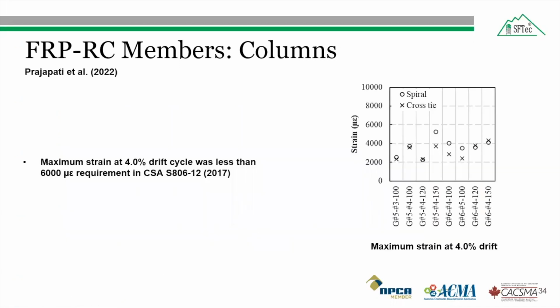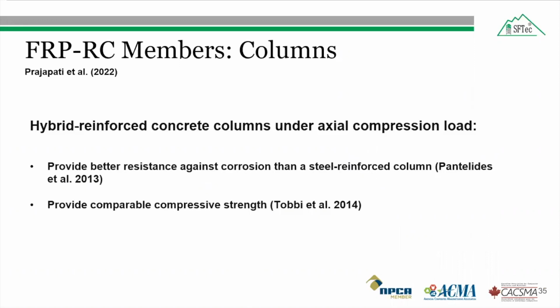The maximum strain attained by all the GFRP spirals and cross ties was lower than 6,000 microstrain, which was lower than the requirement in the CSA S806 design code. The GFRP spirals and cross ties don't show any failure for most of the tested columns, which shows their effectiveness in confining the concrete column core. Glass fiber reinforced polymer reinforced concrete columns could be suitable for medium rise structures in low to moderate seismic zones. The compressive behavior of GFRP bars in GFRP reinforced concrete columns doesn't provide the plasticity required for seismic response, and it makes them more likely to fail in a brittle mode.